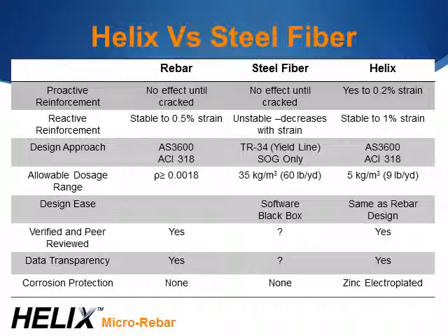We, as I mentioned before, provide any and all data or backup information that you ask for: peer-reviewed reports, tests, third-party test reports, etc. And then also Helix is coated with an inert zinc coating that does not allow for rapid corrosion of the metal. It's been shown to be at least 3 times more corrosion resistant than rebar through Department of Transportation testing.